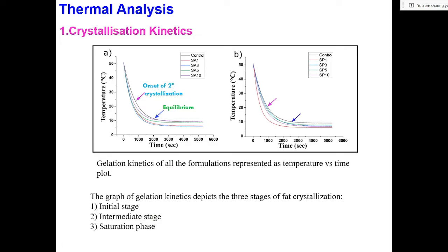Then we performed the crystallization kinetics. Basically, you heat up the sample to a temperature of 60 degrees centigrade, then you incubate the sample in a 5 degrees centigrade water bath or whatever, and you continuously measure the temperature with time. The profile you get is regarded as the crystallization kinetics. Now all these fat based systems show three stages. The initial stage, where the fall is nearly linear, then an exponential decaying stage, which is called the intermediate stage, and lastly the saturation stage, where the fat crystals grow and undergo saturation.